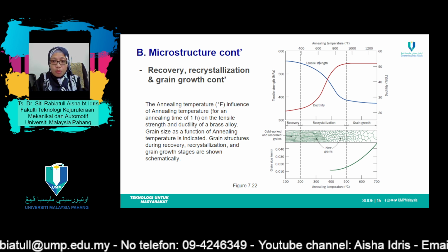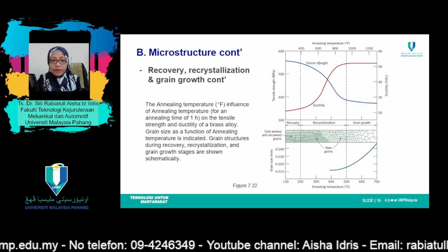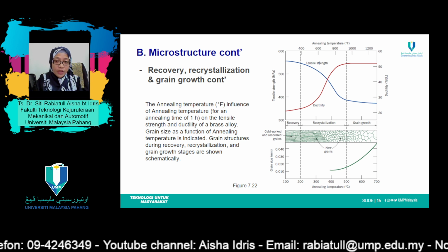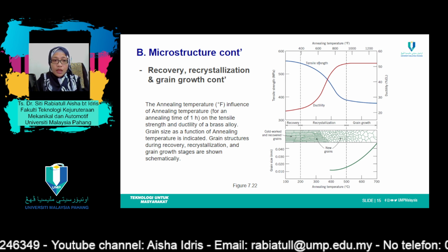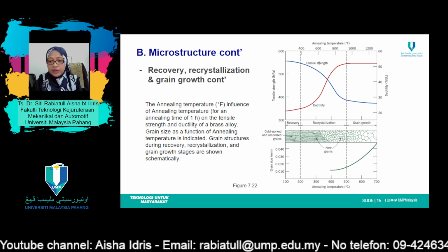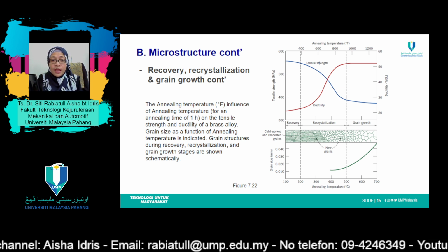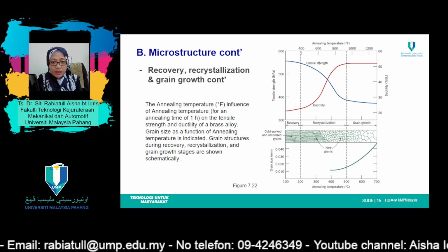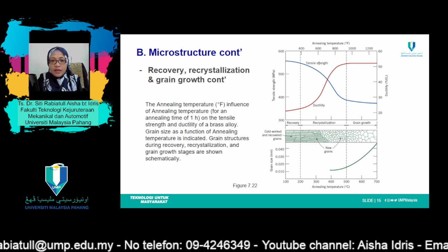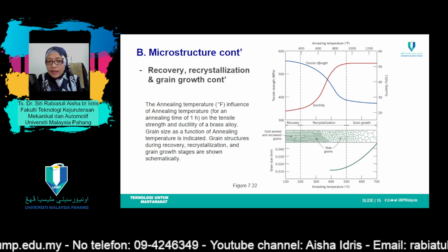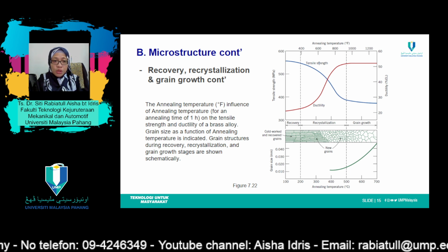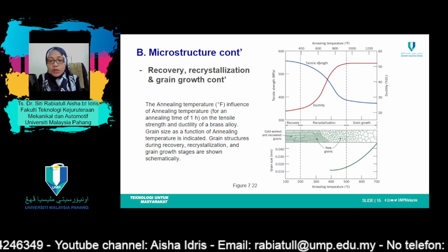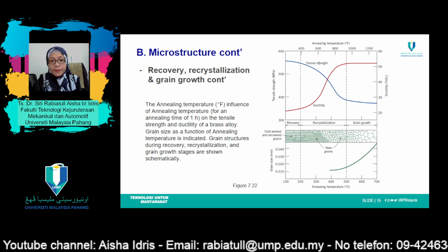Increasing the percentage of cold work enhances the rate of recrystallization, with the result that the recrystallization temperature is lowered and approaches a constant or limiting value at high deformations. Furthermore, it is this limiting or minimum recrystallization temperature that is normally specified in the literature. There exists some critical degree of cold work below which recrystallization cannot be made to occur. Normally, that is between 2% and 20% cold work.